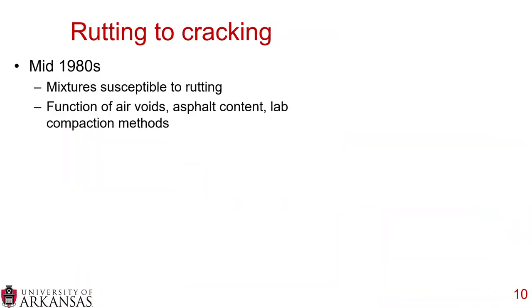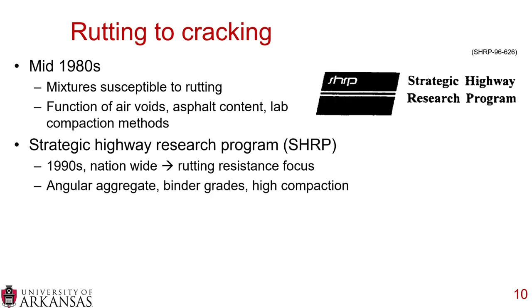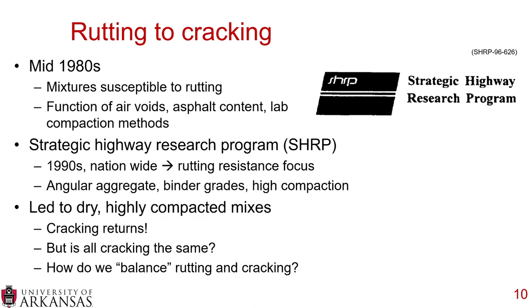But then after the fatigue cracking work had been done at Nottingham and Berkeley, we started going from cracking to rutting. So in the mid-1980s, it was determined that mixtures became very susceptible to rutting. And this was a function of air voids, asphalt content, and the lab compaction methods. And so this led to the development of the Strategic Highway Research Program, or SHRP. And this occurred in the 1990s, and it was a nationwide study here in the United States. And really a main focus of this work was rutting resistance. And they did a lot of work on angular aggregate, binder grades, and high levels of compaction. So what happened? This led to dry and highly compacted mixes, and the cracking returned.